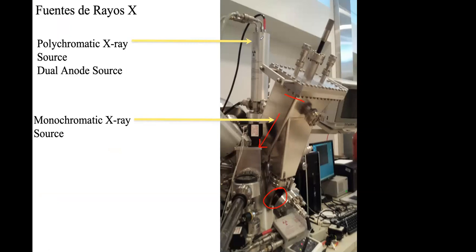This is the polychromatic. One thing that I didn't mention is that the X-ray emission is not very efficient. When you hit your anode in the X-ray source with electrons, much of the energy is released as heat. To avoid the aluminum or magnesium anode melting, literally melting, you need to cool it. So you have a water cooling system, and you cool your anode. Here you have a cooling system too. Somewhere here, you see the two pipes? That's for the cooling system. If you don't do that, you might have an accident in your system because the source might melt and you have water coming in, and it will be a complete mess.